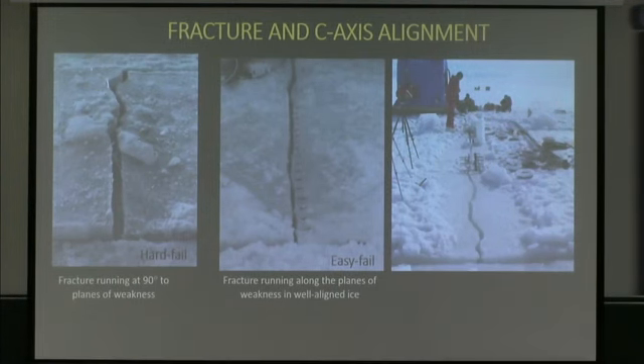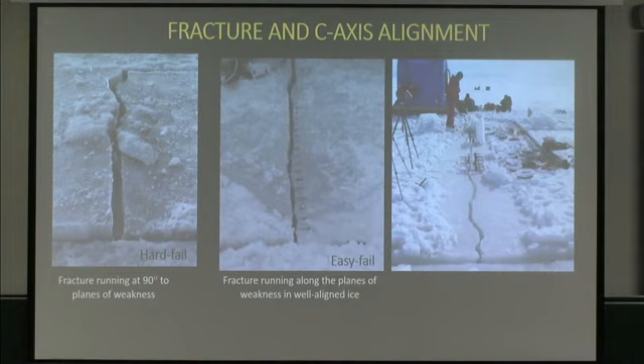The cracks themselves, we talked a little bit about alignment. It turns out that actually, the individual grain alignments and how they get organized have a lot to do with how the cracks run and the fracture mechanics. If the C-axes are all aligned in a certain way such that their planes of weakness make a long scale pattern, then fracture energy goes down. It's a lot easier to break along that direction. You get these very nice straight, smoother crack paths.